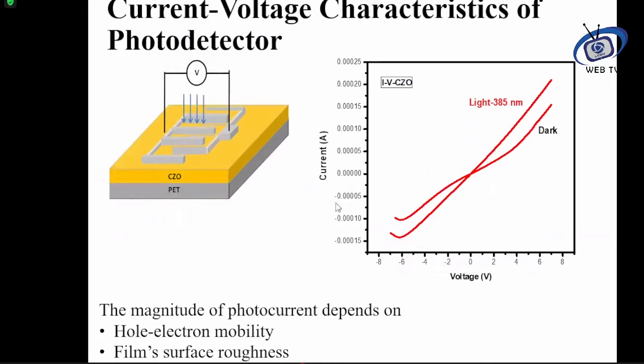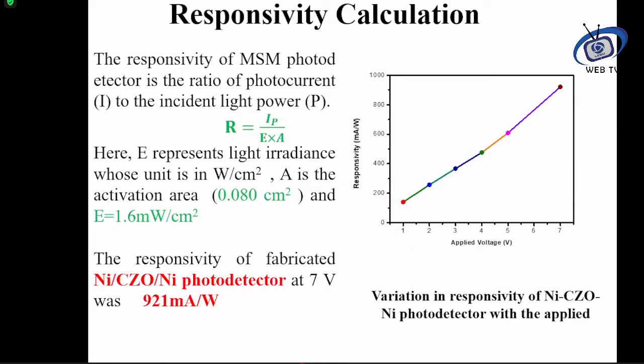And then we checked whether we have found the photodetectors. So we developed this copper doped zinc oxide film, and here we have some connections onto the film. Under the light, we observed that the current increases as we increase the voltage, and if we don't have the light, then it has a smaller current flowing. Then we check the responsivity of the film, which is the photodetector.